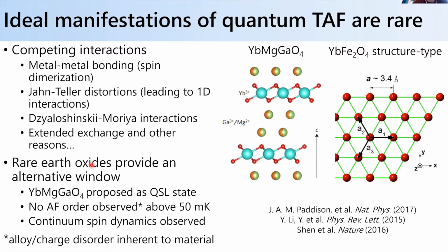And so one of the reasons that rare earth oxides on the triangular lattice have recently become of interest is because they can get around a lot of these problems, meaning extended exchange is typically quite weak, and rare earth ions are pretty versatile in fitting a lot of different lattice types. They are nice, ideal moments to try and understand and model the ground states you're getting. And so I'd say in the triangular lattice, one of the big events was the material ytterbium magnesium gallium O4, which was proposed as a quantum spin liquid ground state.